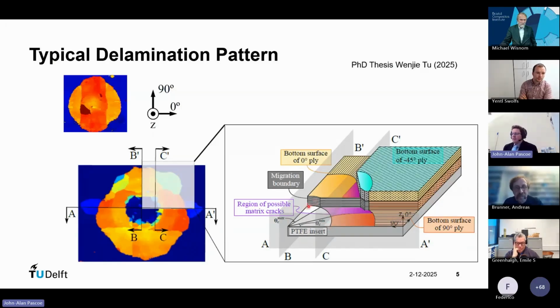So we have the insert in this plane. We see that in this direction, the fibers are exactly aligned with the delamination growth migration, so radially out from the center point. So there it stays in the plane. So that would be mode 2, yeah, exactly. Then on this area, if you do it with VCCT, you would calculate a mode 3 component. So there it immediately migrates, and then probably this is again local mode 2, let's say.